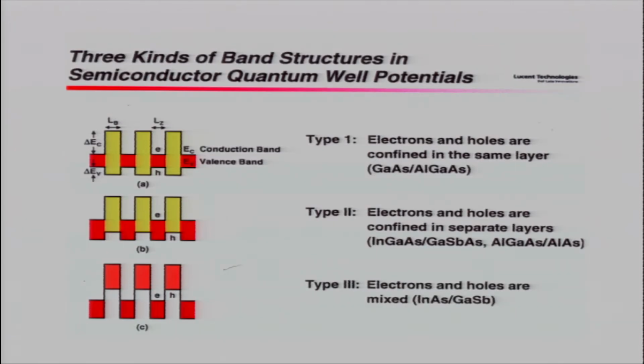As you know, superlattice structures depend on what compound you use to make them. The band alignments are different. You can align them in type 1, type 2, type 3 different alignments. In one, you can have electrons and holes in the low band gap material layer; in another, the electron is in the low band gap material and the hole in the high band gap material; or they are mixed, depending on whether you are growing gallium arsenide, aluminum gallium arsenide superlattice structures, or indium gallium arsenide, gallium antimonide arsenide, depending on what compound you want to use.